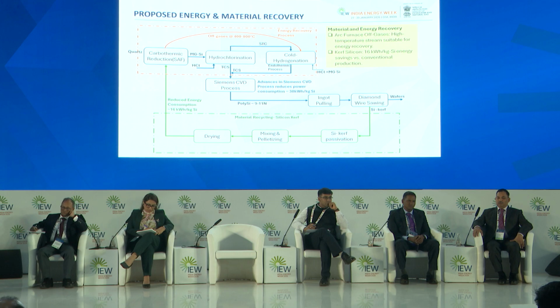If you see the first orange block, that is the energy recovery process. In your carbothermic reduction, you have off gases that are generated at very high temperature. These high temperature off gases can be used to run certain reactions which are there in the polysilicon process. The polysilicon process has two major steps: hydrochlorination as well as cold hydrogenation.